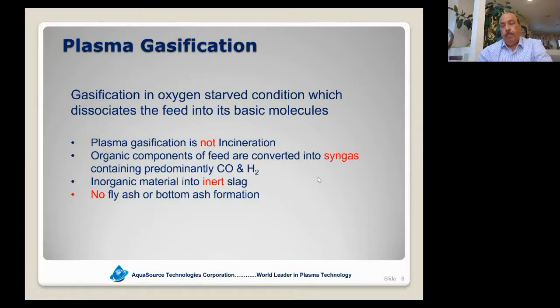removes the pollutants of the feed, the chlorines and the sulfur, etc. The inorganic material of the feed is converted to inert slag, which is basically a feed to the cement kiln. And the most advantageous point I want to impress, besides the syngas volume being very low compared to the combustion volume, since the volume is low in that reactor that I showed, there is no fly ash generation. The fly ash and bottom ash are converted to this slag before the constituents become fly ash to exit from the reactor. So the syngas exiting from the reactor is very clean in terms of particle loading.